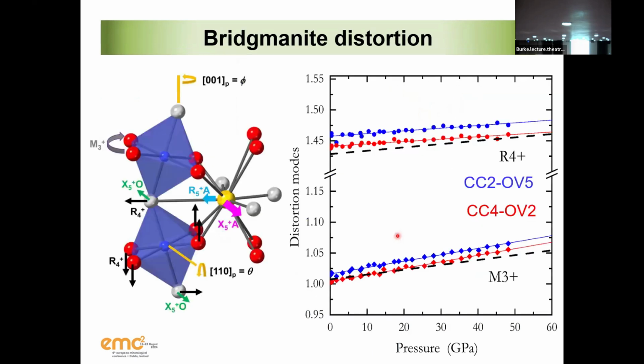Of course, we can also look at the tilting. You know, bridgmanite is a distorted structure from the cubic aristotype. So we can look at the movement of this tilting, which is represented here by what they call the R4 plus mode, which is this displacement of the oxygen in this direction. So this is my out-of-phase tilting, right? And then the displacement of the oxygen in this direction along the C-axis, which is this M3 plus, is my in-phase tilting. These are the largest distortions of the bridgmanite structure.